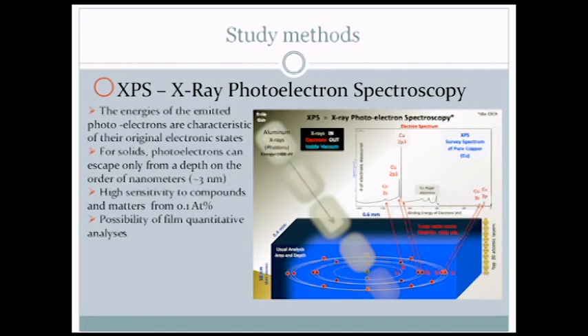Afterwards, the chemical composition of the samples was studied with X-ray photoelectron spectroscopy. Here you can see a small scheme where the X-ray light goes on the surface of the substrate, and emitted electrons are studied with an electron analyzer, and due to these spectra which we received, you can understand what materials there are, for example, here is copper, and each material has a unique spectrum, and if copper, for example, is oxidized, the spectrum will change because of bonding and changing of electron levels.